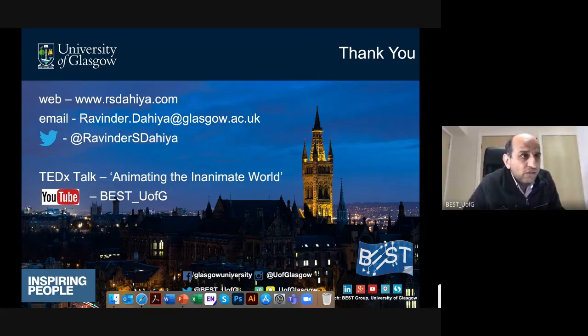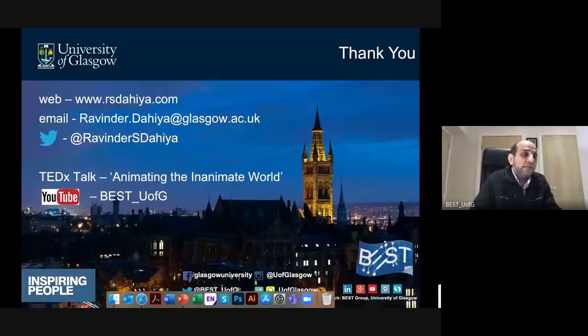There's a question, okay, sensors can be used in many different fields. I have a question regarding suitability of material in harsh environments. Devices were sandwiched between polyimide; how can the device behave at high temperature, and durability? It's a good question because there are several applications where electronic skin can be used and harsh environments would be needed. My answer here would be polyimide is a suitable material, particularly if the harsh environment has high temperature. Polyimide among various flexible materials is the best because it can withstand up to 400 degrees. Others would melt at 150 to 200. So that way polyimide is slightly better.